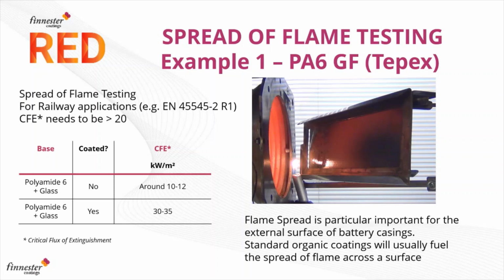once it's ignited. And this is really important to demonstrate how the surface will propagate a flame, and also how the technology works, and that we can self-extinguish, if you like, that flame once it's moving away from the cone calorimeter, once it's moving away from the heat source. We're getting some very convincing results there as well. And in this case, this is using the polyamide 6 glass fiber material, the Tepex sheet material from the company Bond Laminates.